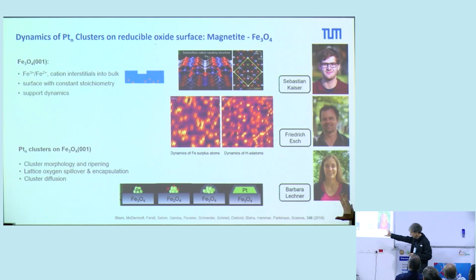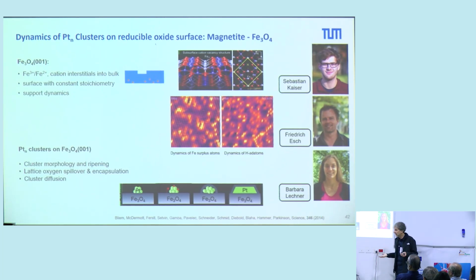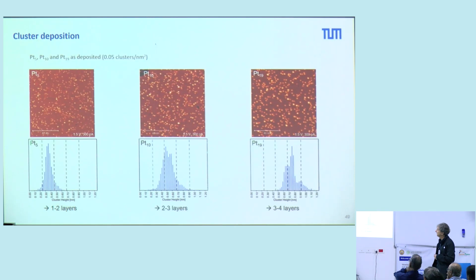And so we are interested in what can happen on the surface with these platinum clusters. Are they stable? Do we have encapsulation? Do we have Ostwald ripening? Do we have Smoluchowski ripening? Smoluchowski ripening is when the clusters themselves move on the surface, they coalesce, and they produce larger clusters. These are the questions we were asking.